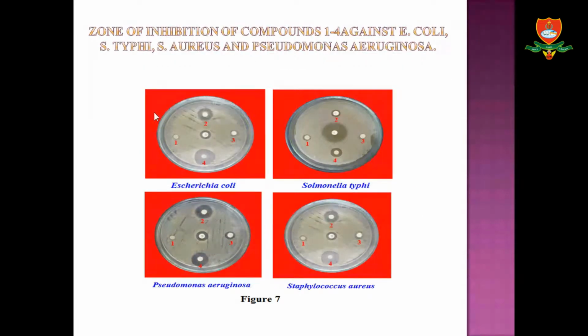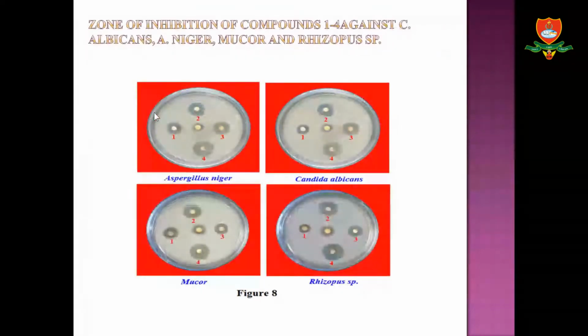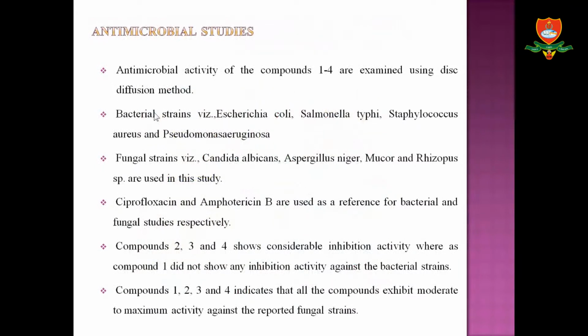This image shows the zone of inhibition of compounds 1 to 4 against bacterial strains. And this image shows the zones of inhibition of compounds 1 to 4 against antifungal strains. The synthesized compounds 1 to 4 are examined for antibacterial activity using the diffusion method. Here, ciprofloxacin and amphotericin B are used as standards for the bacterial and fungal studies.